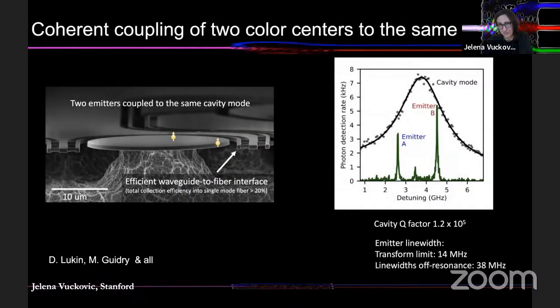And I'd like to show you some really fresh results out of the lab that even bring this on par with diamond color centers. I mentioned earlier on that state-of-the-art for silicon vacancy in diamond is the coherent interaction of two silicon vacancies inside of the same diamond nanocavity, which was demonstrated by the group of Misha Lukin and Marko Lončar and collaborators at Harvard. Very recently, we have shown the same coherent interaction between two silicon vacancy color centers in silicon carbide resonators.